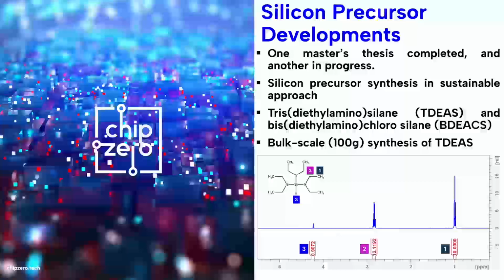So here are our results. The first work package was mostly focusing on silicon precursor development. The main achievement is that we already completed one master thesis, which focused on the screening of the best ALD precursors, together with Volatech. In the beginning, we screened some of the precursors, and then we identified the best suitable candidates and developed these precursors in a sustainable approach. Previously reported syntheses of these precursors used carcinogenic solvents, so we completely replaced these carcinogenic solvents with less harmful solvents like heptane.